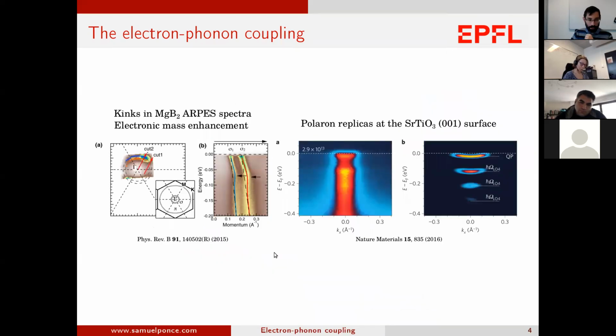If you look at angle-resolved photoemission spectra, this is an experimental way to directly map an electronic band structure, which is momentum resolved. And if you do that for some materials, such as MgB2, you can see some kinks in the spectra. And those are directly linked with an electronic mass enhancement, which again is directly linked with electron-phonon coupling. Also, for example, for strontium titanate, you can have polaron replicas. All those replicas are one LO phonon away from each other.